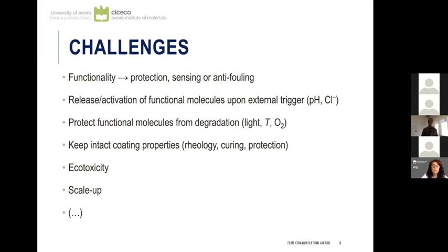coating solution interface. We also have to take into account that the release profiles of the containers that we develop may be different, and is actually different, when we are talking about what happens inside the coating. And we also have to take into account conditions that these coatings are subjected to under service life, like weathering conditions that can lead to degradation of the molecules that we used. And at the same time, one of the probably biggest challenges is to keep the coating properties intact, which means that if we are going to add the particle or the capsule, the coating properties need to be kept.